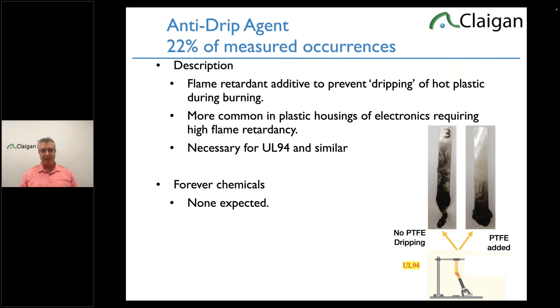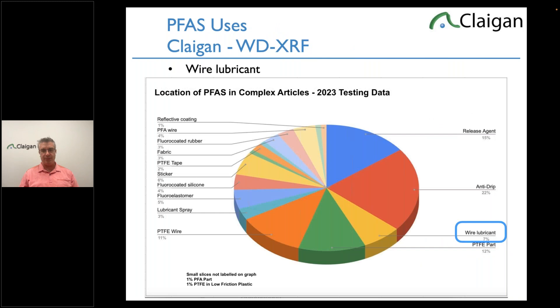Requalifying the flame rating of all your products if you had to change the anti-drip agent would be a major undertaking — and there's no replacement right now. Every housing of yours probably has it, whether suppliers have told you or not. It will be banned in 2027, which would be a nightmare — one of the many reasons we're doing the PFAS submission project. The PTFE powder in anti-drip agent won't have any PFOA because of its construction type — unirradiated PTFE has no PFOA. It makes sense to keep this derogation.